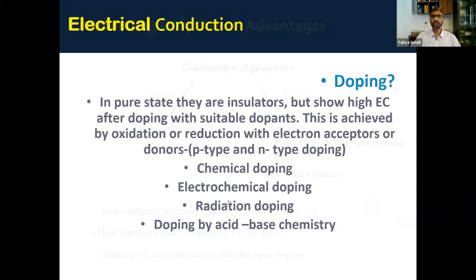I will skip all these things. Doping, you can do different types of doping: chemical doping, electrochemical doping, radiation doping, and doping by acid-base chemistry. Ultimately, after doping, what you get is a radical cation. In the doped state, don't confuse it with doping in inorganic semiconductors. Here, the dopant concentration can extend up to even 50% of the total mass of the polymer. So you have the basic polymer chain, and along the polymer chain, the counter ions are there.